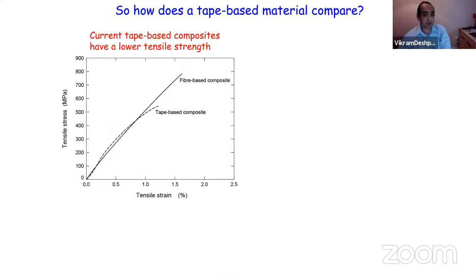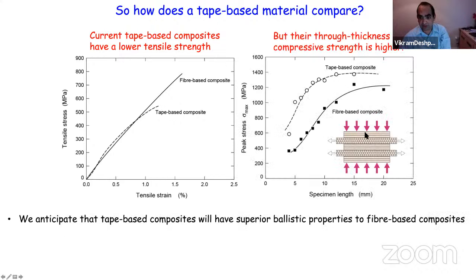And that's what we are trying to do right now, is that this is now a tape composite. Current tape composites have a lower tensile strength compared to the fiber-based composites. But when we do a uniaxial compression experiment, which is really what's happening underneath the projectile, as we have seen, the tape composites are far better than the fiber composites, even though their strengths are low. So we are hoping that the tape-based composites will be better than fiber-based composites, especially if you get the tape-based composites to be the same strength as the fiber-based composites in the tensile strength.